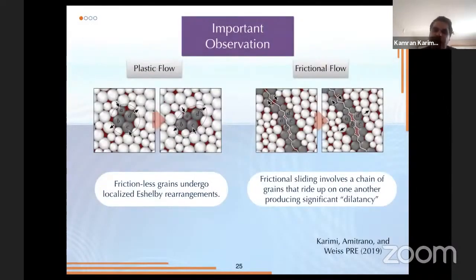We made an important observation in terms of these different elementary deformation mechanisms. In a frictionless system, we see more of a plastic flow type behavior, where particles only rearrange and exchange contact without going through dilation. So the dominant deformation is shear, and it's quite localized in space. Whereas in the frictional flow, we get fairly large blocks of particles that slide past each other, which is accompanied by a large dilatancy due to the roughness of the slip surface.